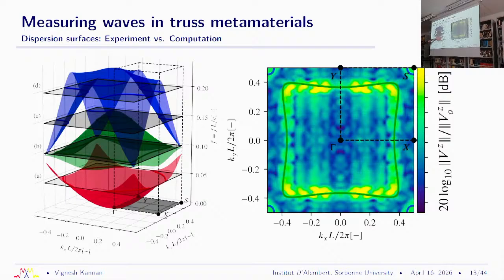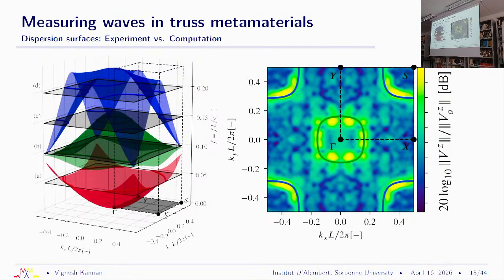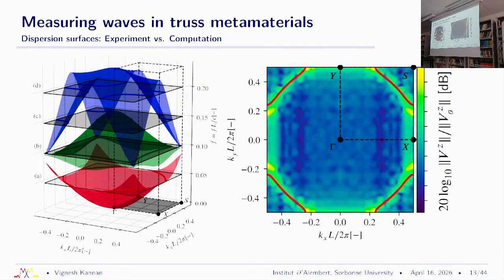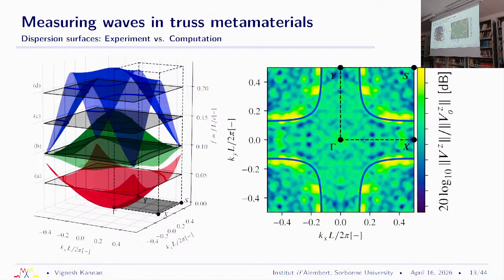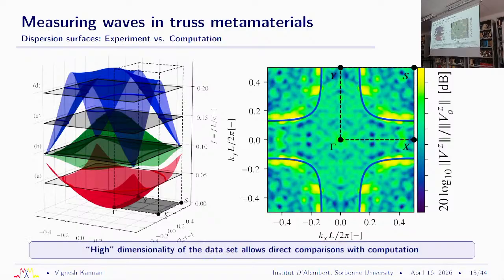And then if we go across these different cross sections, you can actually see that we are capturing these higher modes with very good precision. Of course, we can work on improving the signal to noise ratio, but we were still capturing the essential aspects of our data. And so I'm showing you 4 cross sections through this surface, right? So we were able to capture something up to, if I'm not wrong, the 3rd mode. We weren't able to go much higher than that because of the bandwidth limitations of our instrumentation at the time. So the data set was able to give us excellent information at this time.